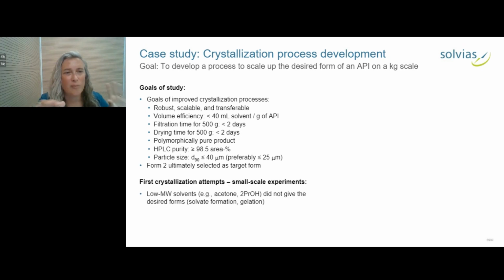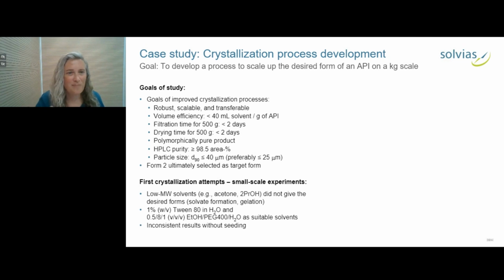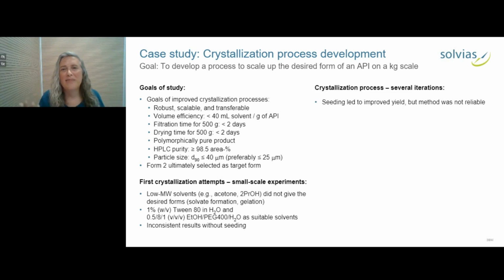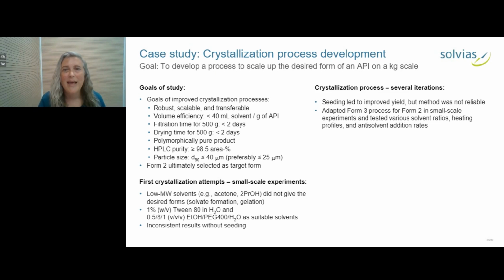As I said, they ultimately selected form 2, so that's what I will focus the rest of this example on. And what we first did was we looked at some low molecular weight solvents, some standard ones, but we did not get form 2 or form 3 from those. Anywhere the solubility was sufficiently high, you formed a solvate, and a lot of times you would observe gels. And so we used a diluted version of the surfactant and also slightly varied the other mixture. And without seeding, we got very inconsistent results. With seeding, we did improve the yield, but the method was still not as reliable or robust as we would have liked. At this point, we decided to adapt the process for form 3 and apply it to form 2 with seeding in some small scale experiments.